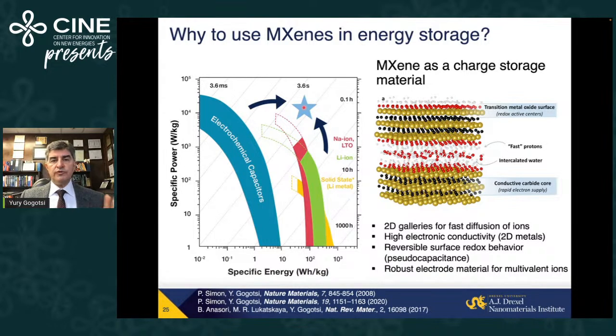But what is also important, what does fast charging mean? It simply means running very high current through the battery or energy storage device. What happens if you run a high current through a poor conductor, like for example oxides in a battery? Joule heating. Now, MXenes are the most conducting materials for electrochemical energy storage today. I mentioned already an order of magnitude more conducting than graphene. Even if you take activated carbon used for electrochemical capacitors, double layer capacitors, supercapacitors, or ultracapacitors.